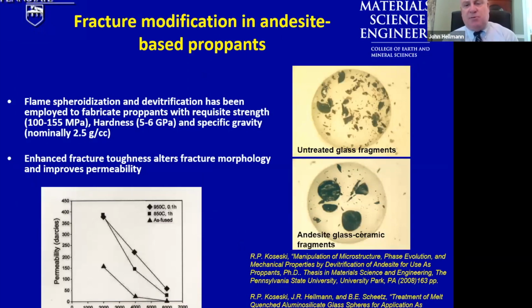fracture was substantially modified after devitrification, going from, in an untreated glass particle shown in the upper right, fine particulate failure that's undesirable, type 2, to the type 1 failure, large ceramic particles which still prop. This was then reflected in the enhanced permeability of these materials, which compared very, very well with industrial materials that were being supplied as proppants to the oil and gas industry.